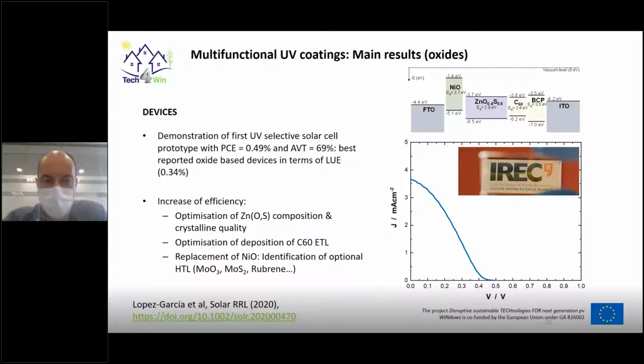We already know that we need to optimize the deposition of the C60 electron transport layer to optimize the uniformity. We are also working on the replacement of nickel oxide as a hole transport layer, because as you can see, there is a problem we already know from nickel oxide: there is a strong discontinuity in the band gap structure between nickel oxide and zinc sulfide, and this leads to a strong limitation of the open circuit voltage that can be achieved with these devices.